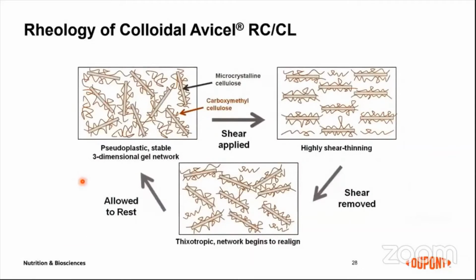And this is the rheology of colloidal MCC. From the very beginning in this suspension sample, you can see the small particles of MCC surrounded by CMC polymer chains, right? So the particles and the polymer randomly array in these 3D networks. But when you have a shear force or shaking, you can decrease the viscosity immediately. So we call it the shear thinning property.